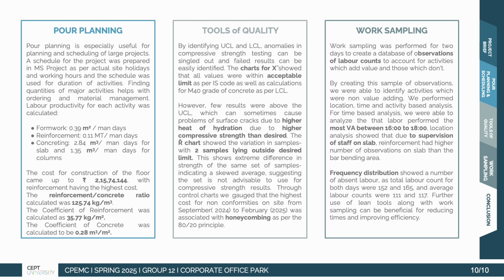For tools of quality, we identified UCL and LCL through which we were able to identify anomalies in the compressive strength testing. The chart for X bar, however, did not show any anomalies as all of the observations were within acceptable limit as per IS code as well as calculations. However, few results were above the upper control limit, which generally does not cause problems. However, it may cause problems due to higher rate of hydration due to the higher compressive strength.